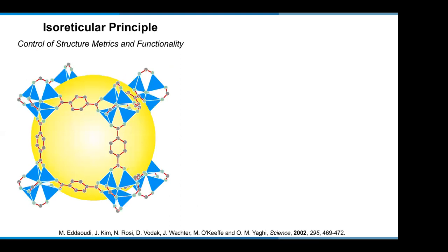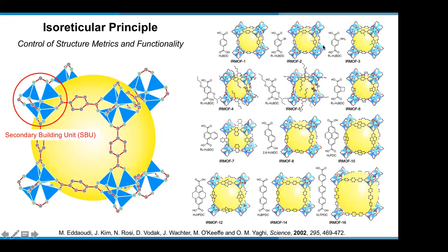So once the power of the SBU approach and the strong bond approach not only gives you porous material, but also, because your frameworks are robust, one can use the same reaction conditions that produce these SBUs, but with different linkers. So you could have a linker that is functionalized, same length, but a different functionality, and therefore have MOFs with functionalized pores, or MOFs that have progressively longer and longer links to make same structures. We call them isoreticular, same underlying net, but now with progressively larger pores.